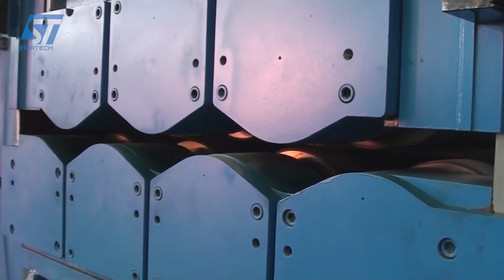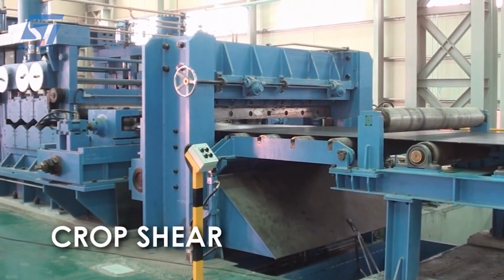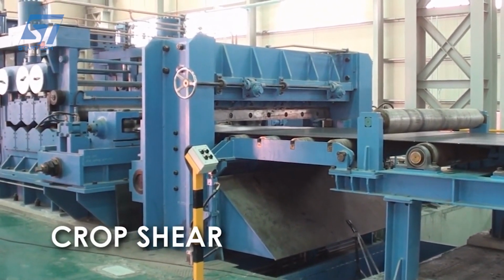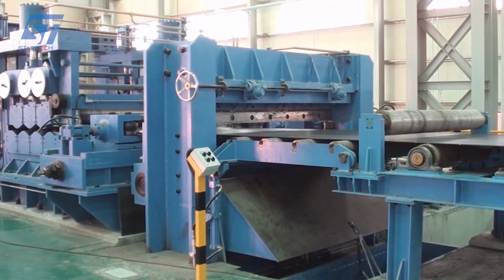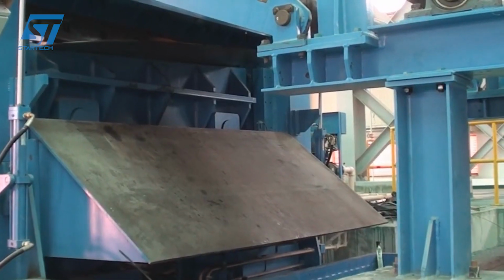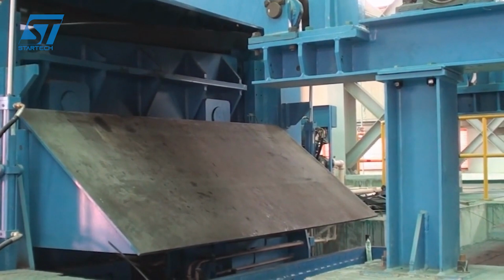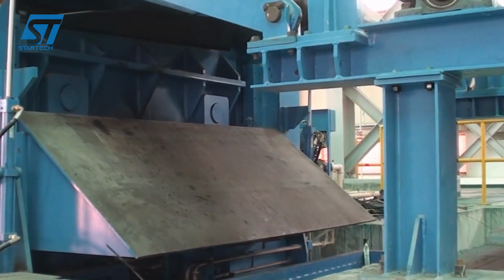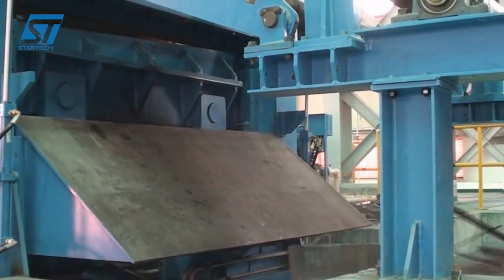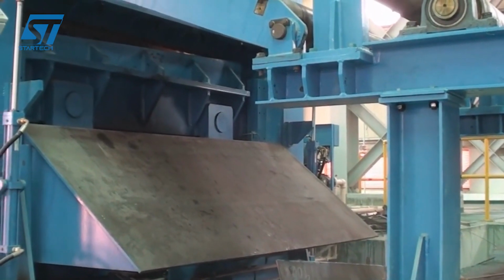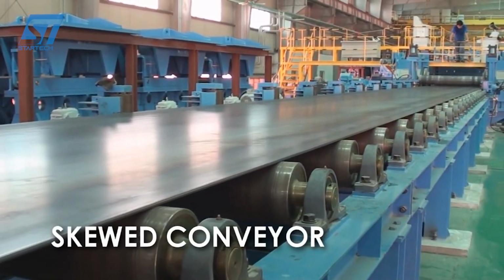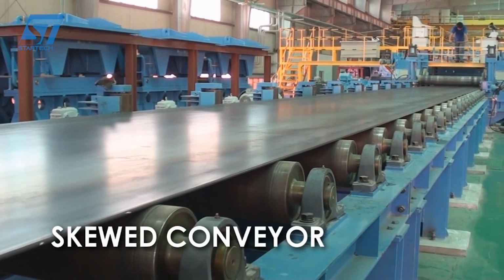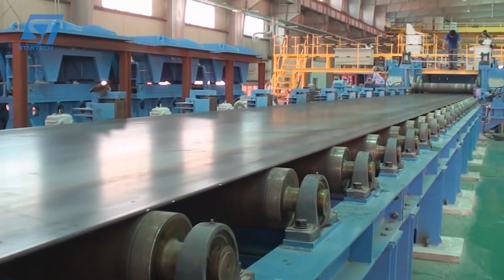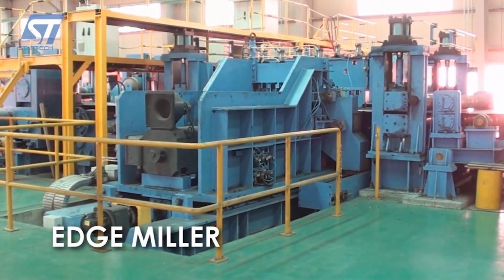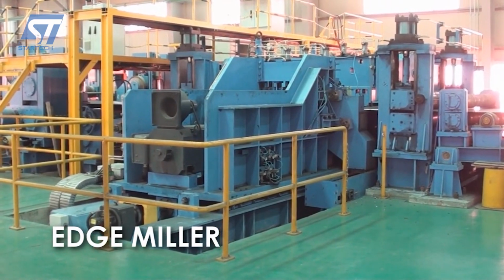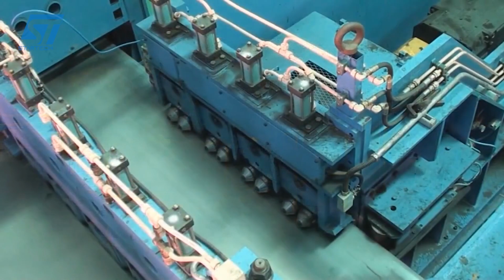In this installation, 2 of the 4 racks were eliminated. Instead of using 475 HP motors, forming was provided by only 275 HP motors. The cage system required less forming effort, and therefore the steel strip was subjected to less stress and deformation and less tool wear. This method becomes especially important and essential when the ratio between the outside diameter of the tube and the wall thickness, i.e., the D/T ratio, exceeds 40:1 and up to the 100:1 range.